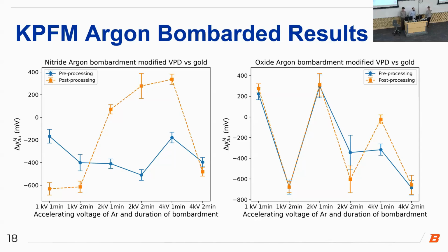That's a great area for future study. We would attribute this basically to the probe and the exact humidity of the room. Since this is done at atmospheric pressure in air, there's a lot of temperature and humidity effect on the actual probe and the measurements when they're being taken. So again, as this is qualitative, I think it's more apt to look at the difference between the pre and post treatment than between different samples.